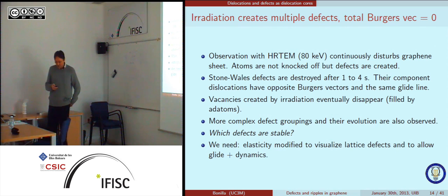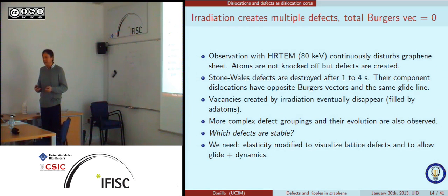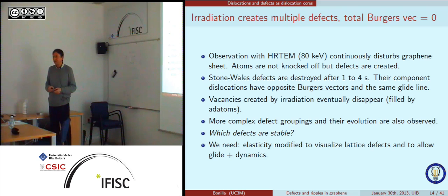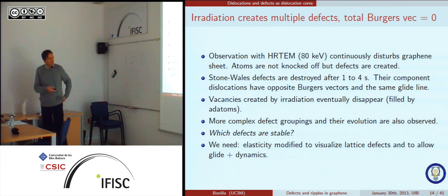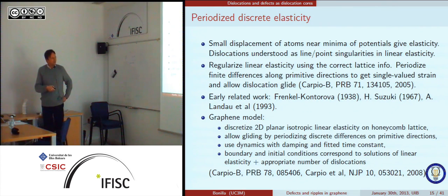So now one thing that you see when you study dislocations in elasticity is that they are line singularities in 3D or point singularities. So the strain and the stresses are singular exactly at the dislocation point. Of course, on a lattice, these things do not happen because everything is discretized. So that was what we wanted. We wanted to modify elasticity minimally so that we would avoid the singularities and give back the symmetry that you lose when you go from the atomic lattice to elasticity. And then this thing that we modified should allow the defects to glide. Okay, so this is what we did.